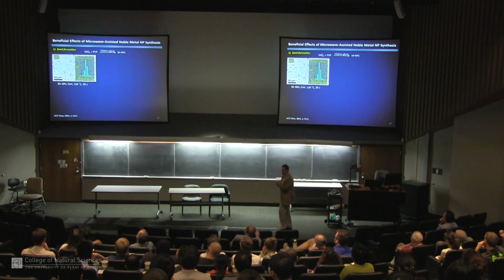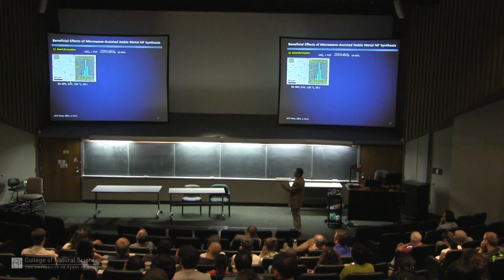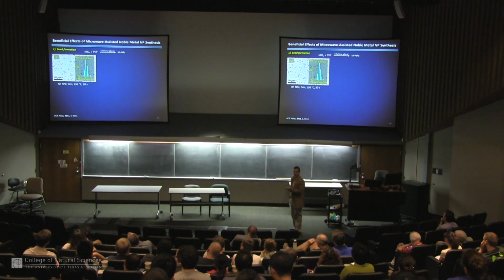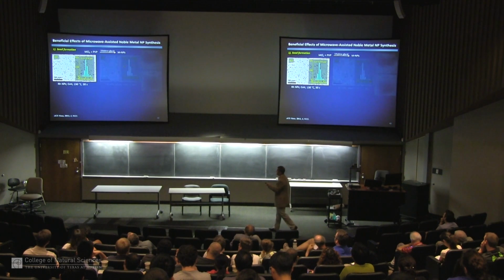And so we've kept the chemistry simple in that we want to make this universally applicable. Simple metal precursors, rhodium, platinum, palladium, iridium, simple, cheap organic polymers, and simple, cheap solvents. So nothing special. We haven't played around with the precursors, but using microwave synthesis to really see the difference. And we saw initially in this initial work a couple of years ago that under conventional heating, if you did this addition of rhodium to the solution, after just 30 seconds, you get these very poorly formed clusters that are really polycrystalline, and they have nothing going for them that's good.